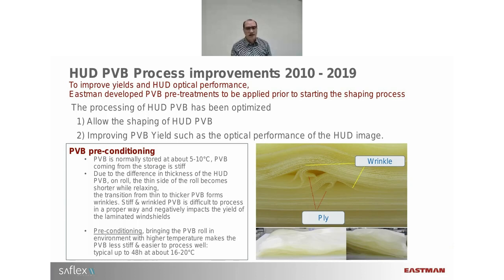In any case, both phenomena can cause yield losses at the lamination site, which of course are to be prevented. By putting the PVB in a preconditioning, meaning in general about 1-2 days at 20 degrees, the PVB becomes more soft and easier to transform from roll to sheet size, which is improving the yield significantly.